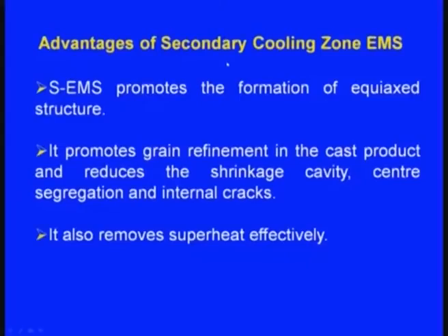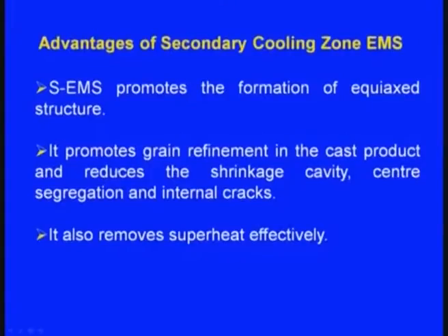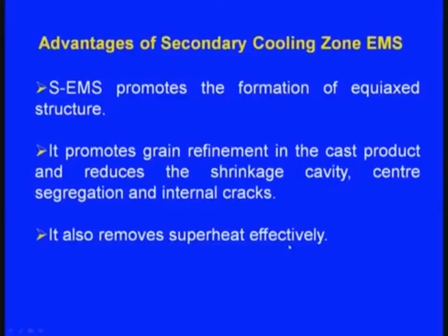Now, these are the advantages of secondary cooling zone EMS. SEMS promotes the formation of equiaxed structure, again a very important and most required property; we will be getting equiaxed grains. Next one, it promotes grain refinement in the cast product and reduces the shrinkage cavity, center segregation and internal cracks. Next one, it also removes superheat effectively. Once we remove this superheat effectively, the solidification becomes faster.